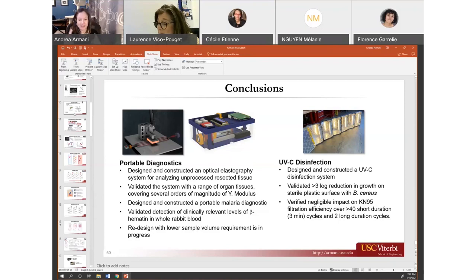But we found we could actually detect the samples degrading, the enzymatic activity kicking up. And so we found we could reproducibly get measurements if we took measurements within about 2 hours after resecting from the animal. But if we waited somewhere between 2 and 3 hours, then the samples began to change, and it kind of depended on the animal and the health of the animal to start.